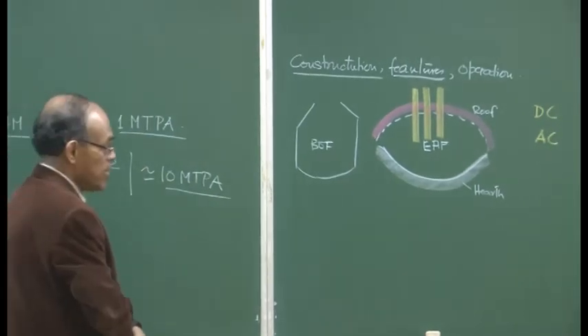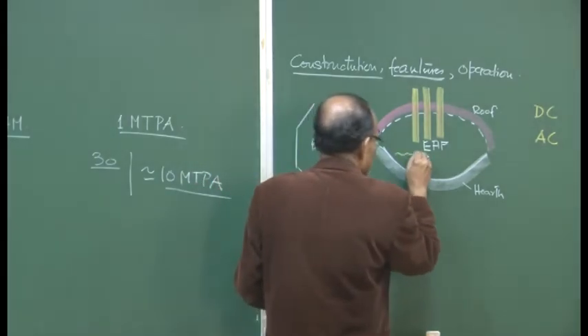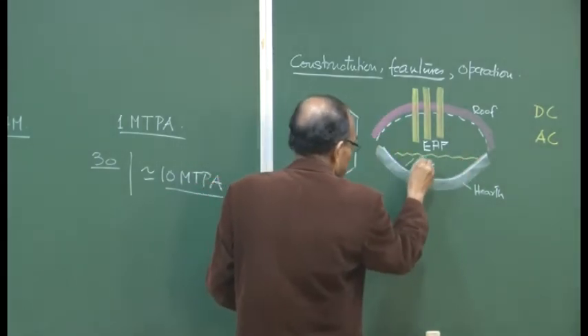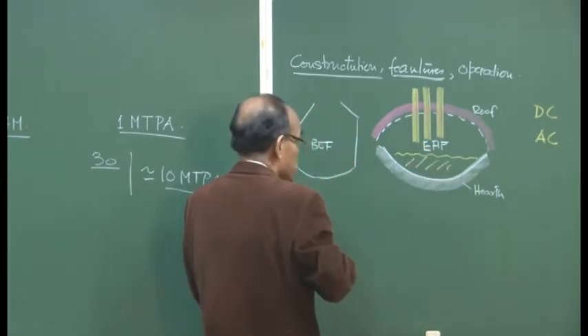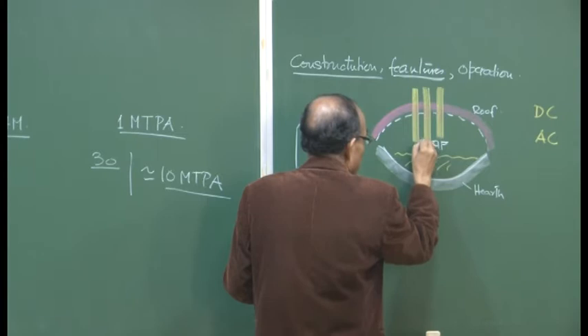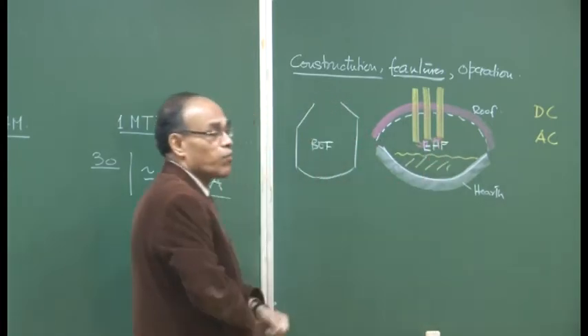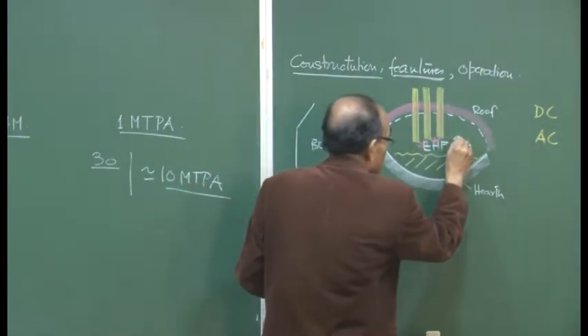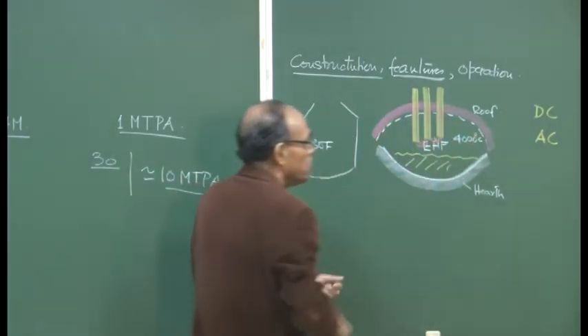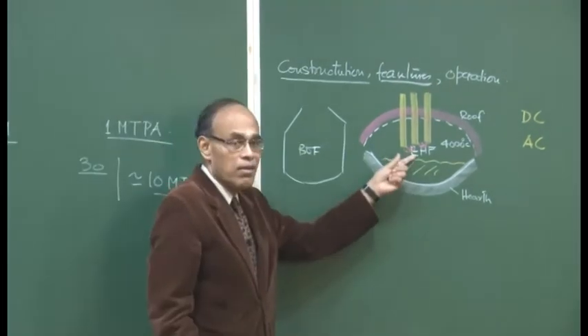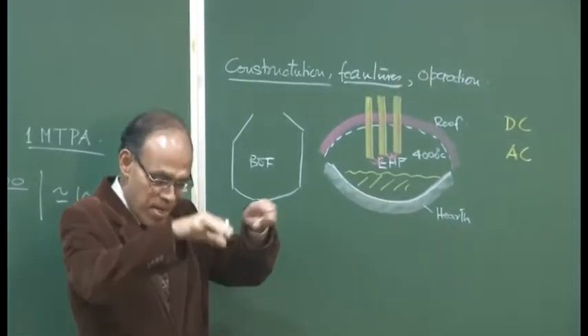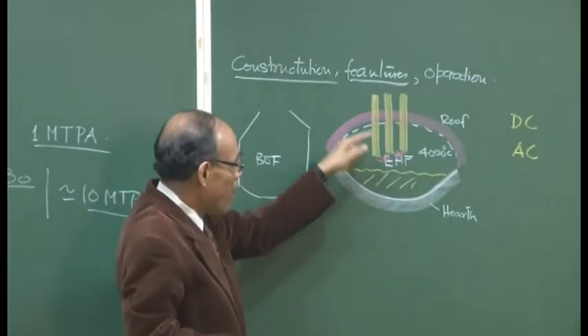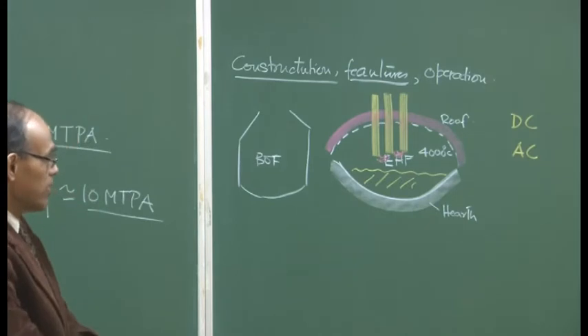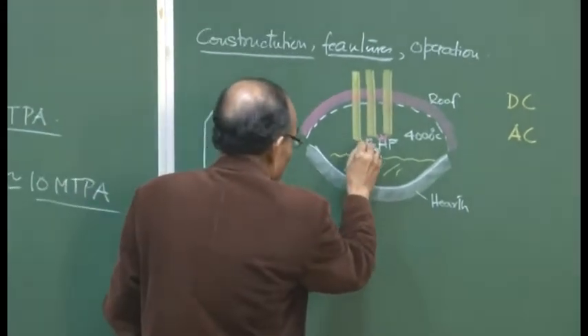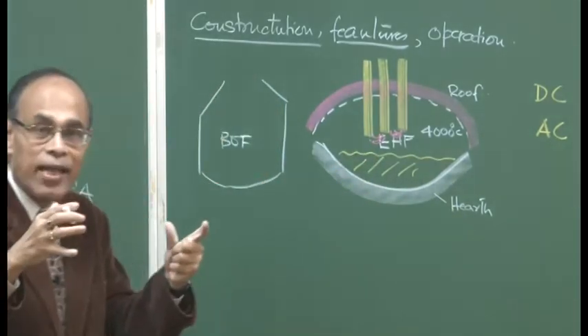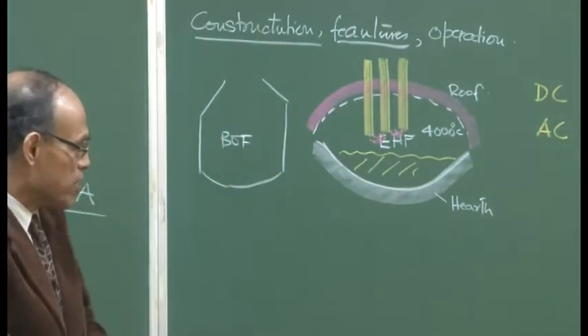So, it is an AC furnace basically, and then what happens is that you have the molten metal here, and there are arcs which are struck between the electrodes, and this arc produces a temperature of about 4000 degree centigrade. The electrode is rarely submerged in the metal, or rarely pushed in. So, this is above the bath, but as we will see later on, when you lower it and the slag becomes a foamy slag, then that tends to engulf the electrode itself. We will see that later on.